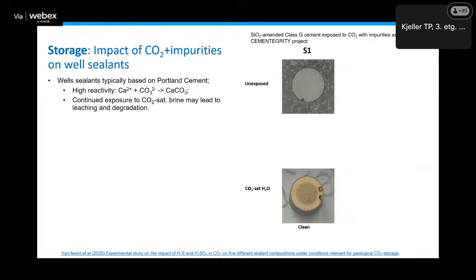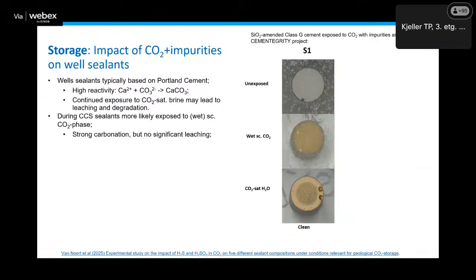At the top, there's an unexposed, fairly standard cement. At the bottom is the same cement after exposure to CO2 saturated water for 16 weeks. Then we also exposed the same sample to wet supercritical CO2. One was placed underwater in the autoclave, one was placed above water, and there it looks very different. We don't see this degraded outer zone where calcite has been dissolved, and instead we see a more gradual change. So carbonation leads to more solid formation and can actually improve the quality of your seal, but leaching will mess it up.